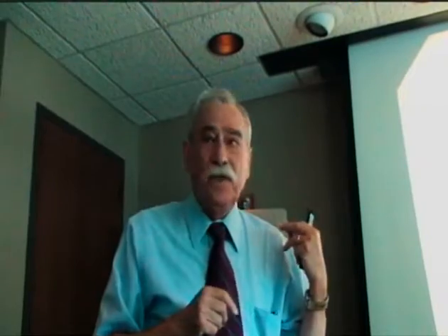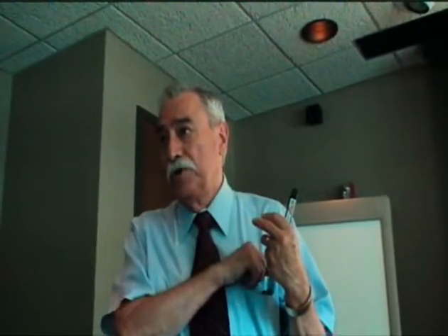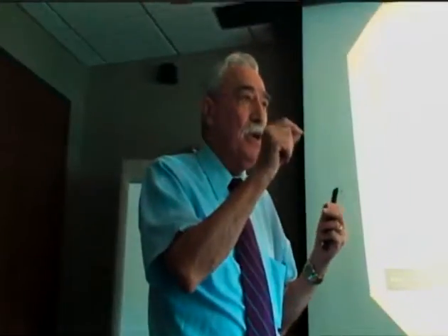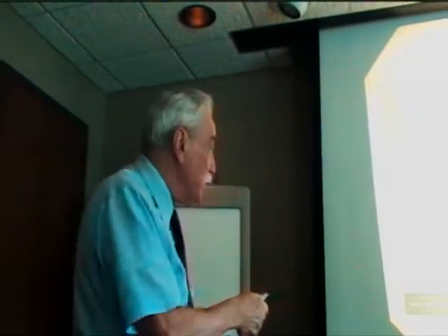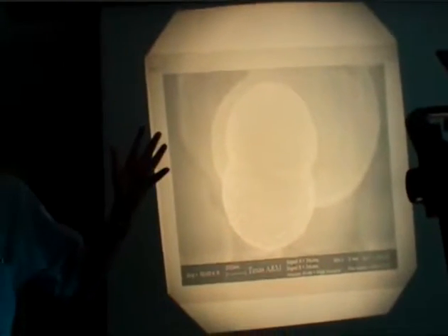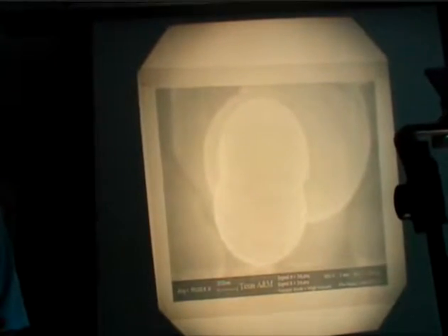Now, as part of the evidence, we have put these things in and grown them for 30 days at 200 degrees. We normally go to about 120 to 140 when we first made these things. And we can see the particles growing bigger and bigger. And surprisingly, what happens is the spheres get smaller and smaller, and the pores get bigger and bigger. So what we think is happening is that you're growing the particles bigger. And if you have a house of cards and you have big particles, you're going to get big pores. See? But the pores are so small here that all the pores are in the micro region.